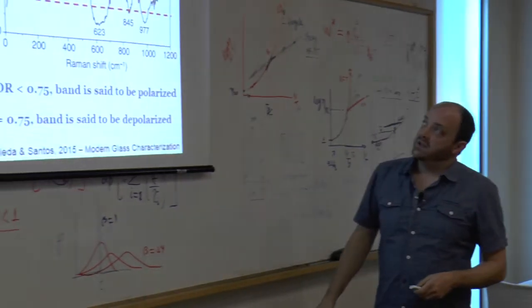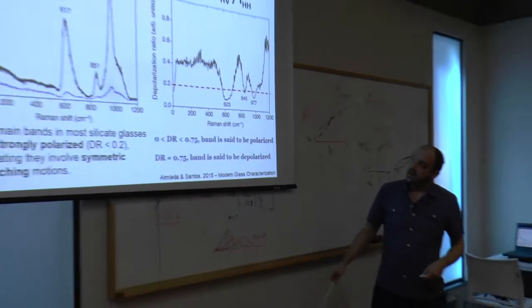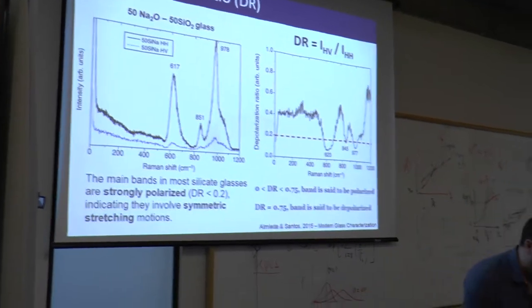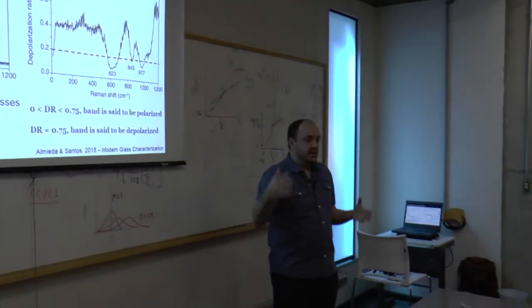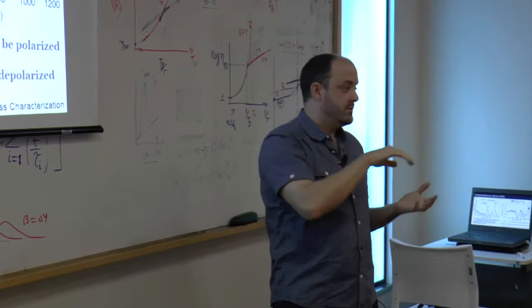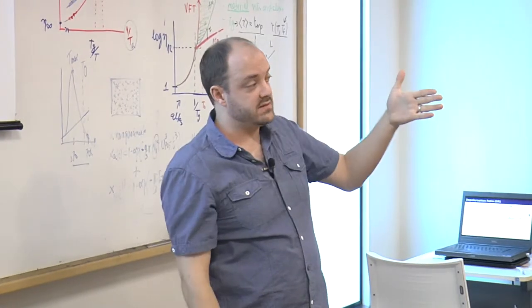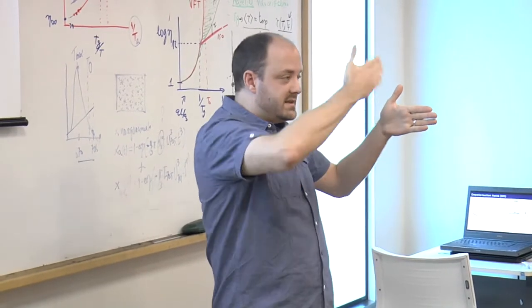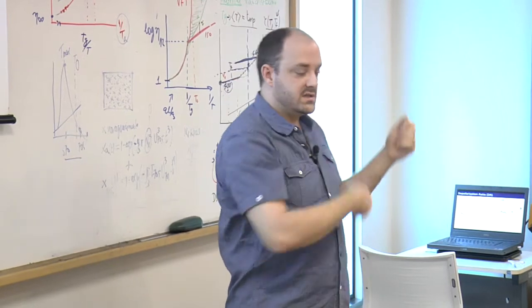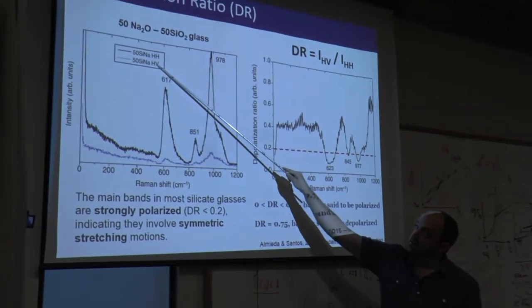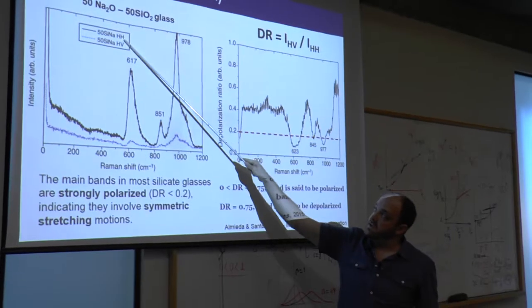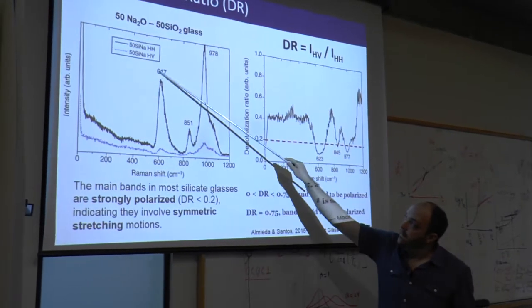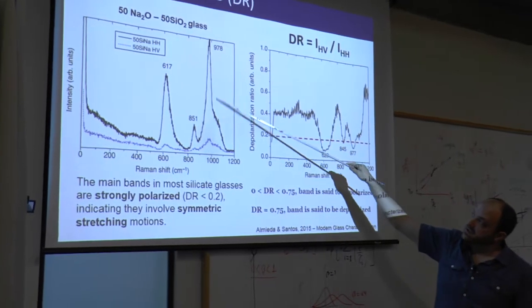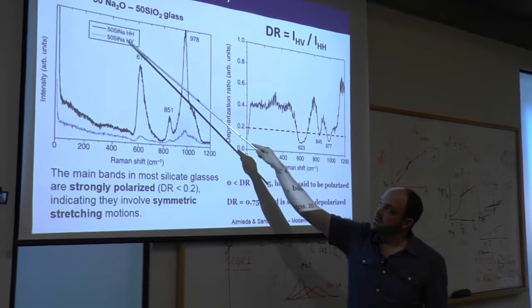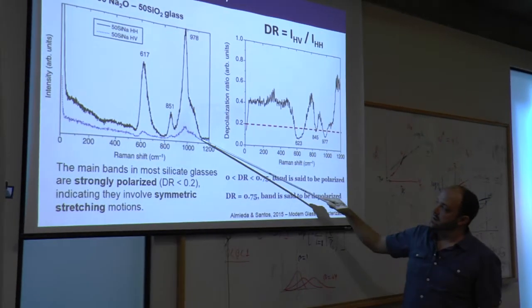Another thing to look at is that a lot of peaks are either polarized or depolarized. So in the polarization process, if you have light that's vibrating in one direction, you can measure the light that's scattered back in the same direction, or you can put a filter that rejects all light except in a specific orientation. So the initial scattering light might be vibrating like this, but you might only look at light that's scattered horizontally or perpendicularly to that. So a lot of spectra have VH, the horizontal versus vertical, and or measured in the same direction, HH. In the same direction, this HH spectra, you get a nice, really strong spectra, but in the horizontally polarized one, you have much reduced intensities.